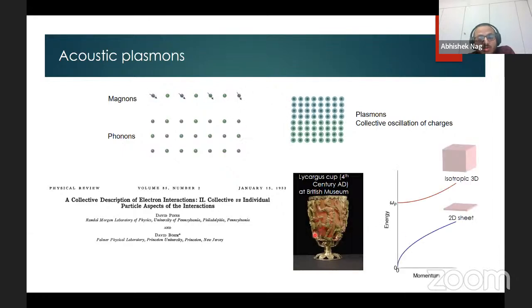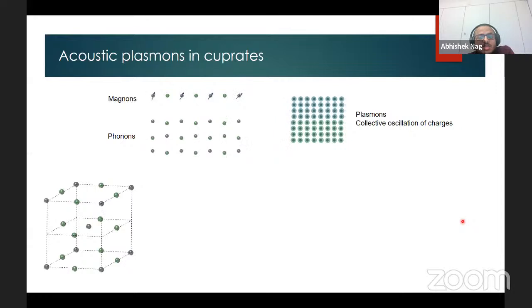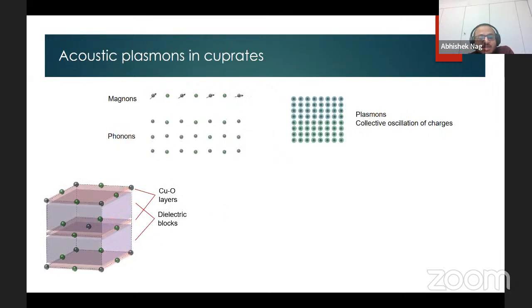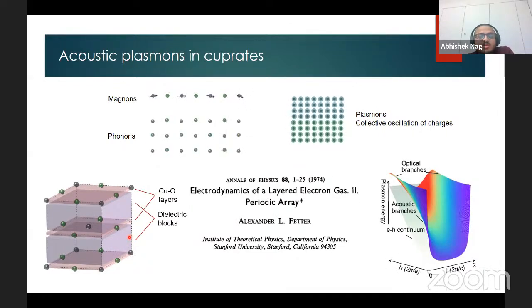Now, there can be different types of plasmon modes depending on the charge density distribution. For an isotropic charge distribution, the plasmon energy has a quadratic dependence and a finite gap at low momentum. In contrast, when the charges are confined to 2 dimensions, the plasmon energies can be made to go down to 0 energy. In the cuprates, however, which have a layered structure, the doped charges reside in the copper-oxygen plane. And this creates a periodic array of layered charges separated by dielectric blocks. Therefore, we have an intermediate situation where the charge oscillations in the different planes can give rise to plasmonic modes which tend to go to 0 energy at small values of in-plane momentum, while for certain out-of-plane momenta, one can observe optical plasmon modes which have an energy gap. And these plasmon branches appear due to the interplay of the interlayer Coulomb interactions in these materials.